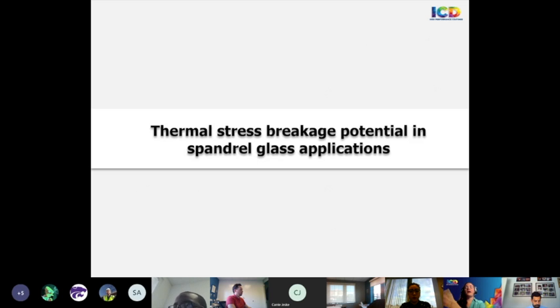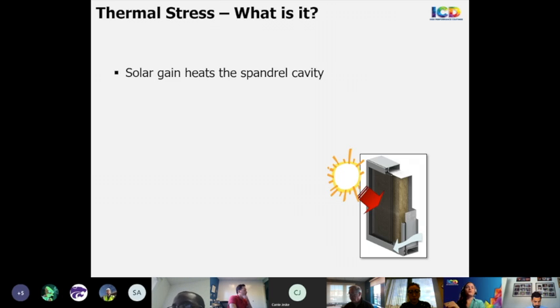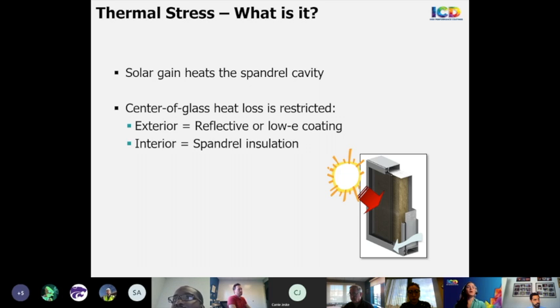So now I'll just show some examples of how thermal stress breakage occurs in spandrel glass applications. So thermal stress occurs because of solar gain, even though there are reflective and low-E coatings that are sometimes used for the spandrel cavity, often used for that visual continuity. Solar heat energy can still get through between the glass and the spandrel insulation, which heats that cavity up. Then the center of glass heat loss is somewhat restricted. So if you do have a reflective or low-E coating, along with the composition of an insulated glass unit, it reduces heat loss to the exterior. And then the insulation, the cavity backing behind the spandrel glass, reduces the possibility of heat loss to the interior.